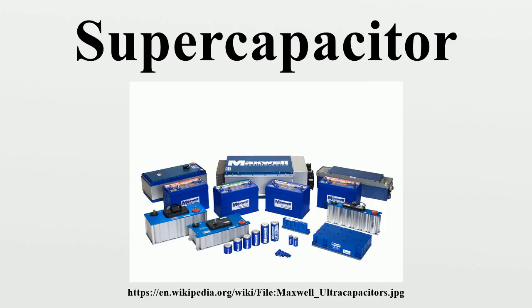Solvent molecules adhere by physical adsorption on the surface of the electrode and separate the oppositely polarized ions from each other, and can be idealized as a molecular dielectric. In the process, there is no transfer of charge between electrode and electrolyte, so the forces that cause the adhesion are not chemical bonds but physical forces. The adsorbed molecules are polarized, but, due to the lack of transfer of charge between electrolyte and electrode, suffered no chemical changes. The amount of charge in the electrode is matched by the magnitude of countercharges in outer Helmholtz plane.